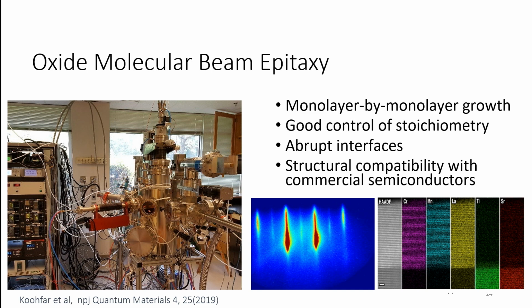And during the growth, we can monitor the crystallinity of the surface using an electron diffraction technique. So this is an electron diffraction technique we can use during the growth to monitor the crystallinity and the symmetry of the surface. And after the growth, there are a lot of techniques we use to actually confirm that we've grown the materials that we would like to grow.